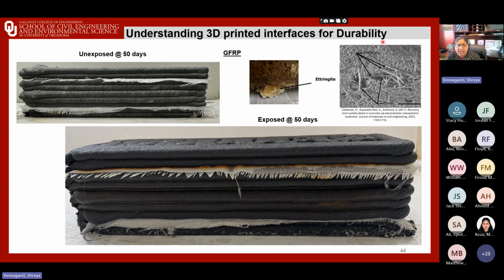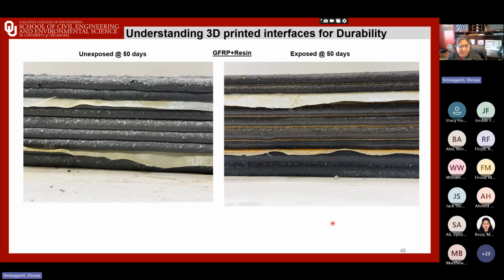This is a past study where they are showing these crystal-like structures. You don't see it more predominantly here, but you will see it in the CFRP ones, more pointing outwards. This one is the GFRP plus resin. I'm going to run through these slides quicker. You see this discoloration as well. Some sort of ettringite being pushed out, not too predominant, maybe because the resin is helping sort of be this barrier towards the chemical ingress.